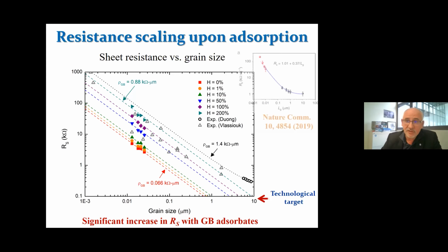And it turns out, this work I just mentioned before by the group of Wencai Ren and Hui-Ming Cheng, for the same value, we enter into the same interval, and we could say, okay, that will correspond to grain boundaries contaminated by, let's say, half of the grain boundary being contaminated. So we have some kind of guidance by comparing simulation and experimental data.